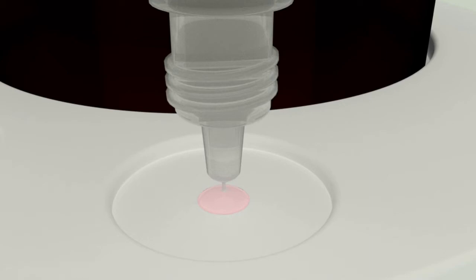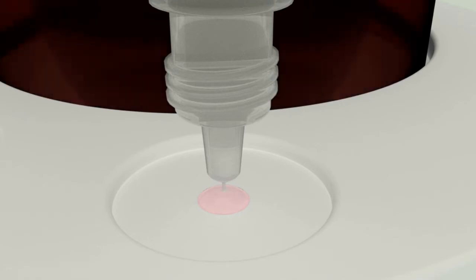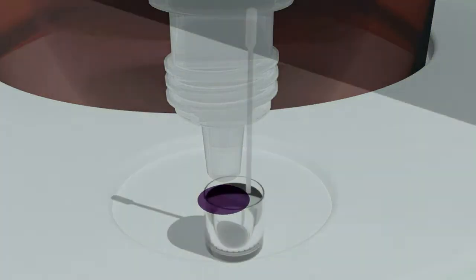If any gold remains dissolved in solution, the sample would immediately turn purple or black. This test is exceptionally effective. Even 4 parts of gold per million parts of solution will cause the sample to change color. If you see a color change to purple or black, give the solution more time to complete precipitation, and then test again. You can test as often as you like.